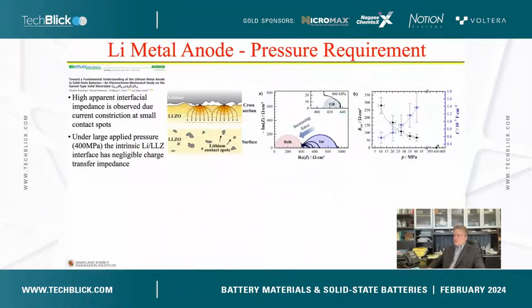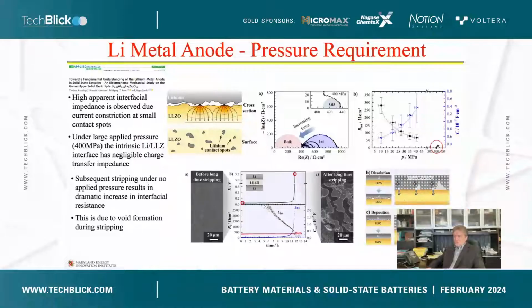A lot of people looked at solid state electrolytes. This is some work by Jürgen Janek's group, and there's very high interfacial impedance. But if you apply enough pressure, you can get the lithium metal to be in good contact with the solid electrolyte, in this case a lithium garnet material. You'll notice that at 400 megapascals, the interfacial impedance goes to essentially zero. The reason for that is that on the stripping cycle, the lithium pulls away from the solid state electrolyte, so you have to maintain that pressure against the cell.